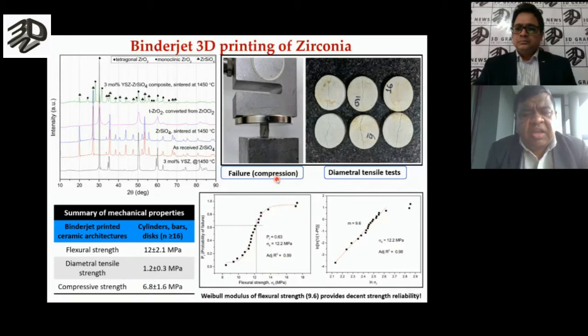While we are able to get a reasonable Weibull modulus, we found that the strength is fairly low. Flexural strength is 12 megapascal and compression strength is less than 10 megapascal, which is really brittle. That means it has a lot of porosity, intrinsic porosity as well as processing induced porosity. Now, to address that, we found that binder-jet 3D printing typically gives you a core shell type of morphology. We have recently patented a technique where this core shell type of printing can be avoided, and we can bypass that by adopting a more intelligent way of processing